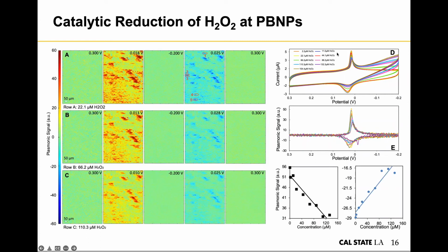And here we have the comparison between the potentiostat CV and the plasmonic CV. You can see that the peak is still there due to the Prussian blue to Prussian white conversion, and the peak current decreases due to the hydrogen peroxide presence, because some Prussian white is immediately pushed back to Prussian blue. And if we use the intensity here at the reduction peak, we can get a linear plot, which is pretty good for hydrogen peroxide sensing at an individual nanoparticle level. So that's the example I would like to show here.